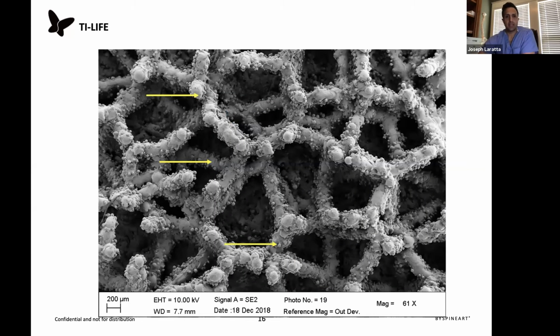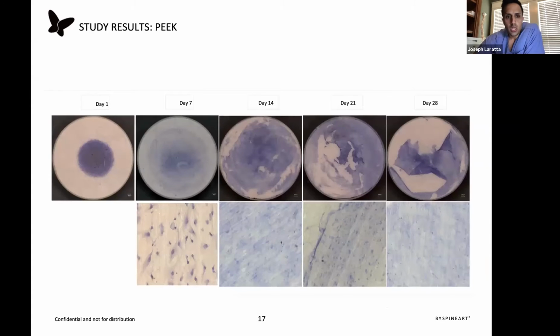When you look at the TiLife technology on scanning electron microscopy, at 200 microns, you can see the trabecular nature of the metal. And if you look really closely, you can see this surface roughness that is purported to improve osteointegration. So these are the results for our PEEK group.